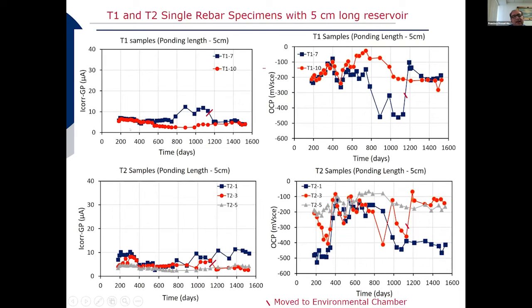Here you see a sample that was actually placed into the environmental chamber, this T1 sample on the top left. You can see that the blue symbols indicate how the corrosion current changed as a function of time, and in this red bracket is when we moved it to the environmental chamber. For this particular specimen, by doing that, the corrosion current decreased to a value that you can still measure, and that is comparable to the other sample that has the same reservoir length, but it has not become as active as it was before. You can corroborate that with the potentials on the figure on the right, which were more negative.